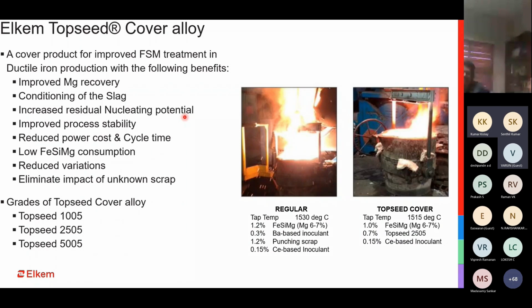But that is not always possible with the covering scraps. That is not always possible with the turnings and borings. Why? Because these covering scraps, these turning borings, one, need a lot of heat for melting, and two, they may bring with them their own set of unknown elements into the system. It can be oil, it can be rust, it can be lead if the scrap is coated or painted, it can be zinc. So there can be many more things which these covering scraps can bring with them. And when you have such a covering scrap, your inoculation and even your ferrosilicon magnesium treatment will not be effective. So what do you do in that case?